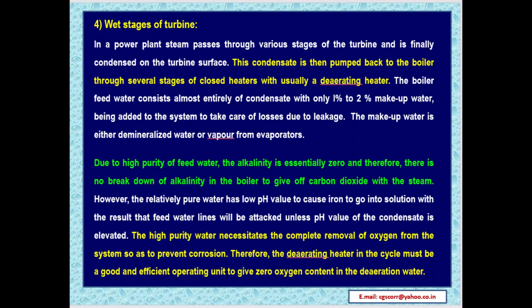Due to high purity of feed water, the alkalinity is essentially zero. Therefore, there is no breakdown of alkalinity in the boiler to give off carbon dioxide to the steam. However, the relatively pure water has a low pH value, causing iron to go into solution, with the result that feed water lines will be attacked unless the pH value of the condensate is elevated.